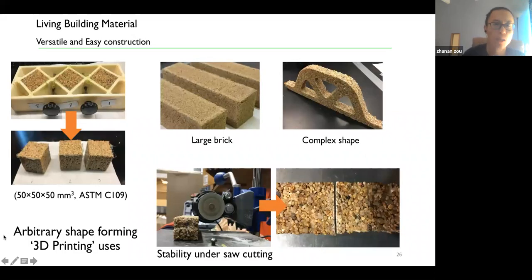Yeah, if you look at the left picture, this is the way that we made this living building material brick. We use a plastic mold, as you can see on the top, to put the sand and the mixture of the gelatin, the cells and the calcite together. And after the cure, we just demold it and leave the brick, as you can see, the cubes, at room temperature for about 8 days to let it dry until there's no mass lost. And also with a similar technique, we can make larger bricks, as you can see in the middle, and also complex shapes, as you can see on the right side.